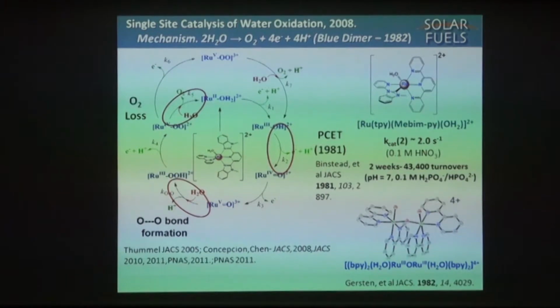This gives an intermediate hydroperoxide, which oxidizes further to ruthenium-4 peroxide, and we have really good spectroscopy and a lot of evidence for these as intermediates. There's no crystal structure yet in these coordination environments. Then an oxygen is lost and the complex re-enters the cycle. Sometimes the system can be hung up here, and the loss of the oxygen can be the rate-limiting step. One way to avoid that is to oxidize it again at an accessible potential, it turns out, to give ruthenium-5, and then oxygen comes out of the coordination sphere and the system re-enters the cycle here. So we know a lot about that part. What about the architecture part?